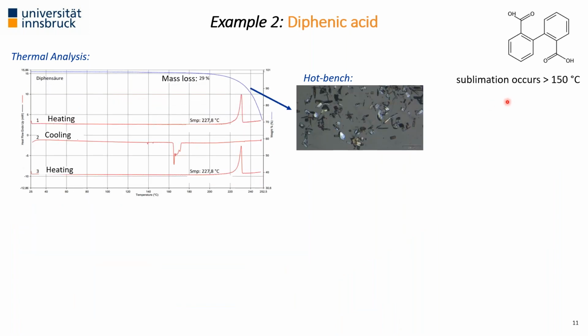So for the next one, we used a little bit more challenging one, diphenic acid. It shows sublimation, as can again be seen from the TGA curve, mass loss, but if you check here, this is occurring at about 200 centigrade, and in the literature it was mentioned that sublimation only occurs above 150. And there we already have problems with organic compounds, because the higher the sublimation temperature or melting point, the more likely it is that decomposition occurs. And when we want to grow some nice crystals and keep the compound for a longer time at higher temperature, especially carboxylic acid functions will start to decompose.